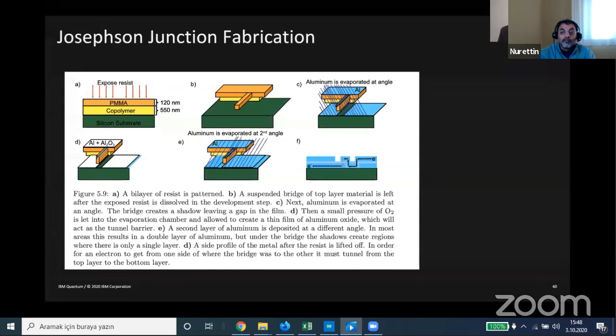As described, the Josephson junction is like a nonlinear inductor. The way we fabricate this is to expose a bilayer photoresist with E-beam lithography. The areas that are exposed are then developed, dissolved in a development step. We end up with a Dolan bridge, as shown here. Aluminum is then evaporated at an angle coming from one side and is shadowed by the bridge. We then introduce oxygen into the growth chamber to form aluminum oxide, and this ends up being the tunneling barrier for the Josephson junction. We then evaporate coming from the other side, at a different angle, and from that we form a junction between the two layers separated by that tunnel barrier. And finally, there's a lift-off step of the photoresist.